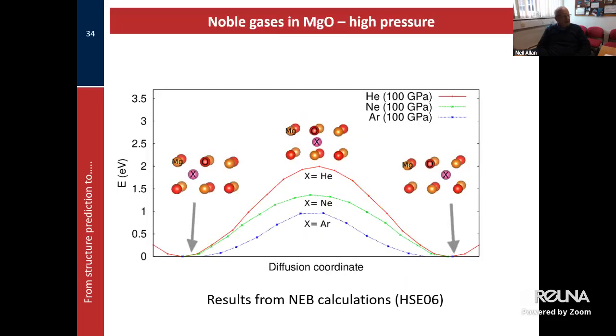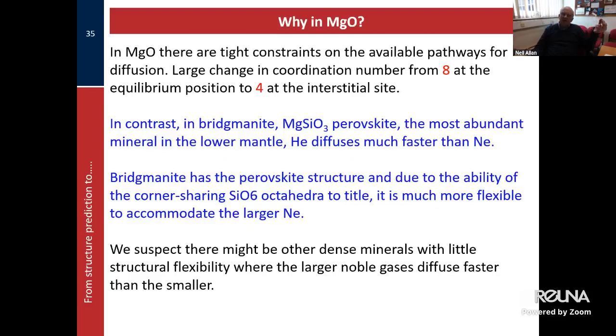We also did nudged elastic band calculations, which showed the activation energies for the atoms moving, that suggested the same thing. We even added argon to our list. That's not what we expected. I don't have time today to give our detailed explanation, but it's a bit like, imagine a shop full of china, plates and cups and things, and I've got an elephant called Neon in it. Well, actually, the elephant is unhappy in the shop, but it's pretty easy for the elephant to move anywhere. It just causes chaos and strain wherever it goes. It doesn't really matter very much what its position is.